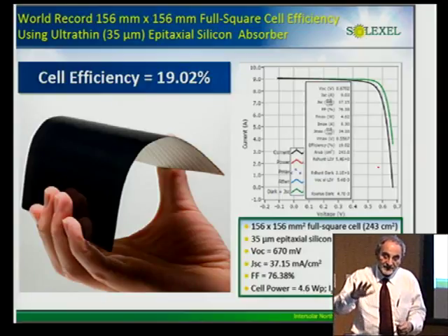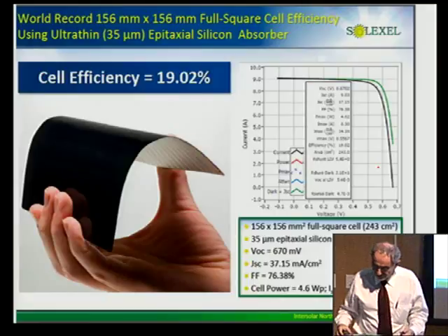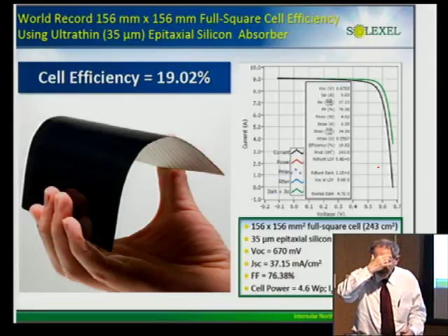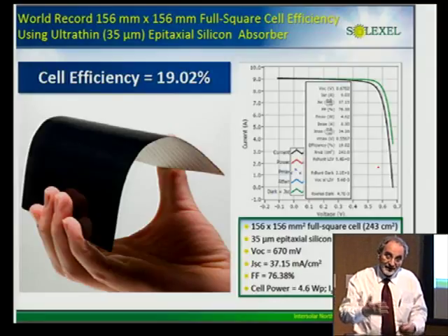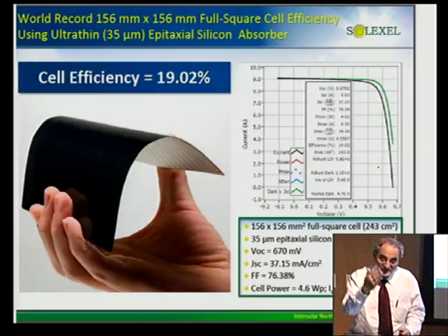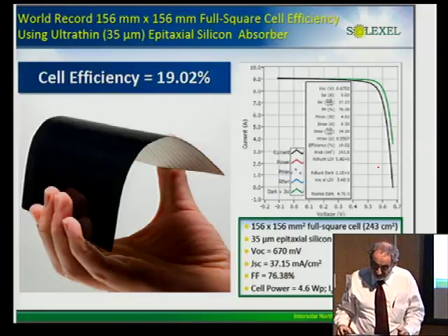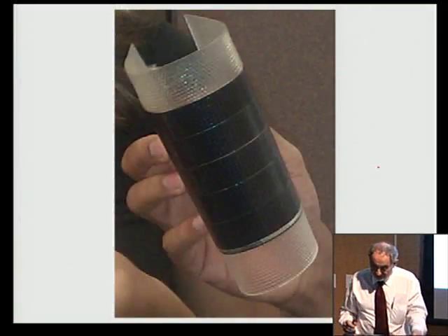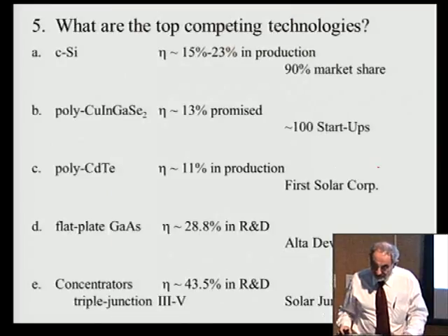You've got to peel the film at the thickness that you're actually going to use. Today, the solar cells are not peeled. They're cut with a saw. They cannot make the saw blade any thinner than about 200-300 microns, and they waste all that sawdust, which is high purity silicon, so it's wasted. And this is another picture of these Alta cells that I was just showing you.